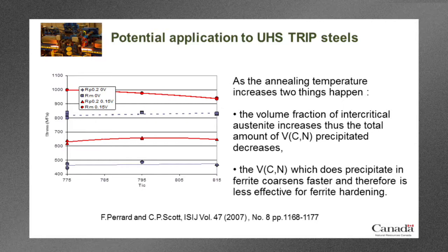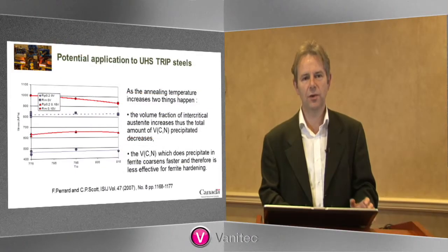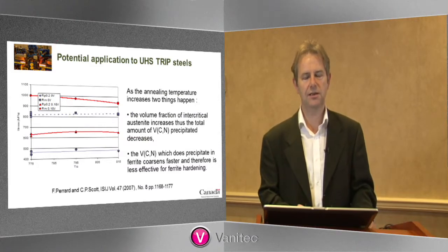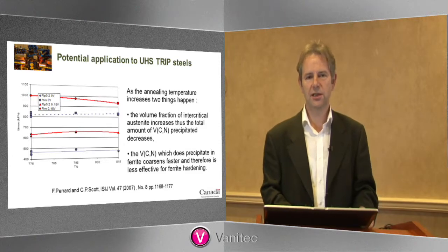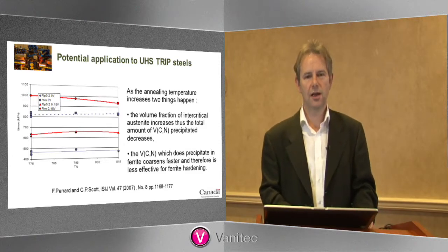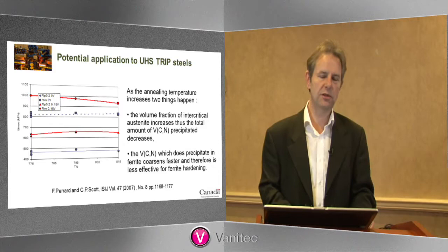Then the vanadium carbide, which does precipitate in the ferrite, is going to coarsen faster because you're at a higher temperature. And so it's less effective for ferrite hardening. So that explains briefly why we get this behavior with annealing temperature. Now the question would be, what could we do about that? There are various possible solutions, which I'll discuss later on.